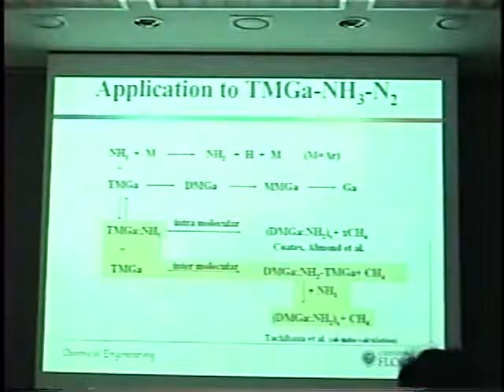So what we have going on is a balance between not forming this polymer, because the polymer takes gallium out of the reaction, but we want to form the adduct because it's going to preserve the gallium and the ammonia for delivery to the surface, where it can undergo reversible decomposition back to trimethyl gallium and ammonia, and we can deposit gallium nitride. So very complex. If we allow this reaction to occur, we'll form a polymer. It takes gallium out. If we allow this reaction to proceed, it forms gallium in the vapor phase. Also takes gallium out of the reaction. We need to deliver this adduct to the surface, and we need to find conditions to do that.